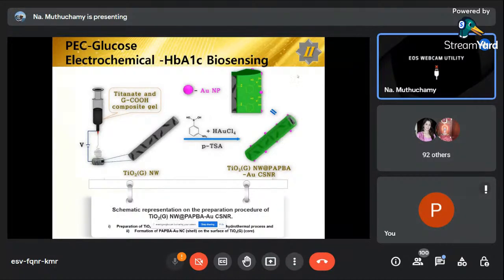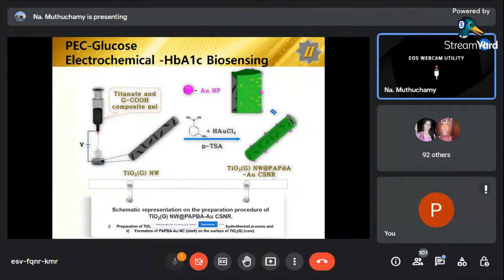In the sensor probe fabrication, first we prepare TiO2 nanowire with the electrospinning method. Then we polymerize with 3-aminophenyl boronic acid. Then we form the shell with gold nanoparticles. Here the gold nanoparticles also play a main role in enhancing the current, as we know that gold nanoparticles have some light responses.